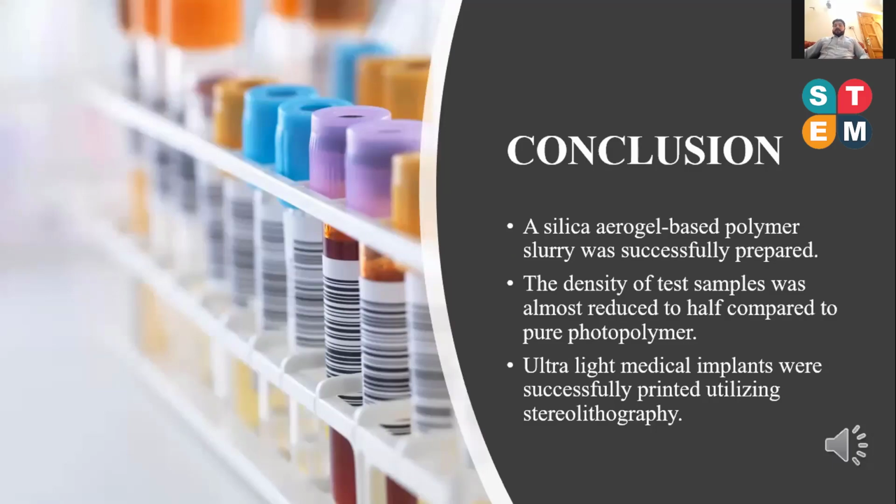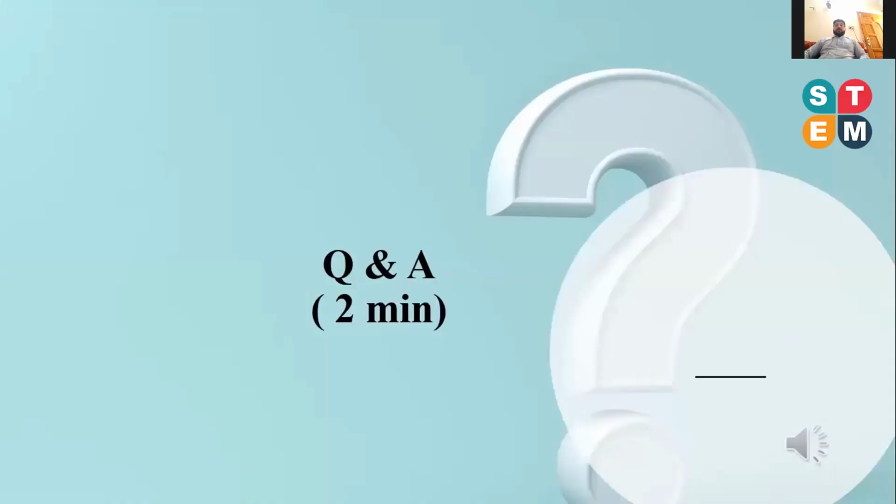The density of this sample was almost reduced to half. This was the main conclusion: by increasing the content of the filler, we were getting a lighter sample, and up to a certain mark we get the best sample. Ultralight medical implants were successfully printed utilizing stereolithography, as we showed in the previous pictures.